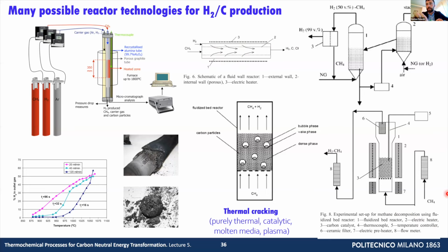Another interesting aspect we're looking into, through funding from the Ministry of University and Research, is a bubbling bed reactor. In molten metal pyrolysis, you have a bubble, cracking occurs inside the bubble, carbon is formed, and it floats on top of the metal. Typically we use tin, and then you release the gas phase products that are hopefully rich in hydrogen, while you're able to clean up the carbon forming at the surface of the metal.